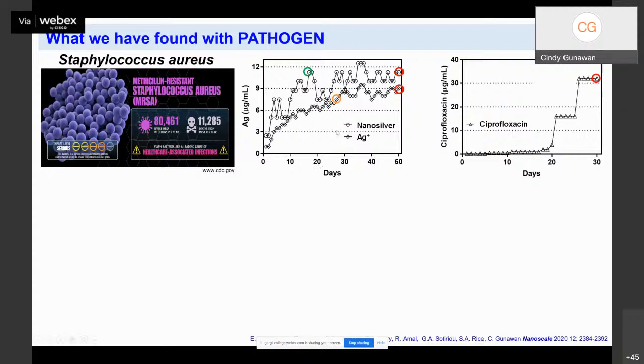And in this study, we're not just studying nanosilver; we also did a parallel comparison with ionic silver, as well as with the antibiotic ciprofloxacin. The study with ciprofloxacin is not just to compare the potentially different adaptation responses of this bacterium to silver in comparison to antibiotics, but also as a validation of the experiments, because we already know that Staph aureus can develop stable resistance to ciprofloxacin. So this is what we did.